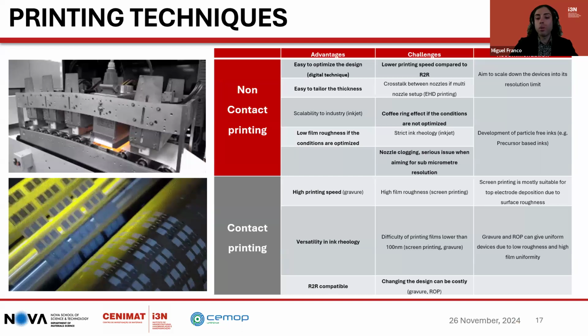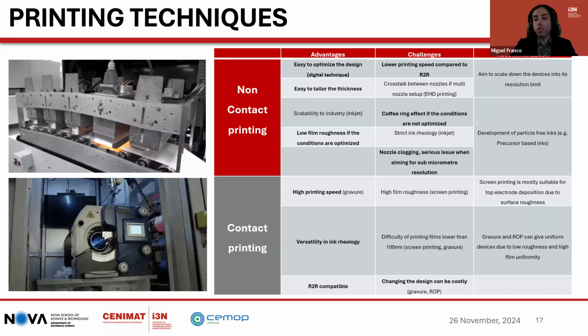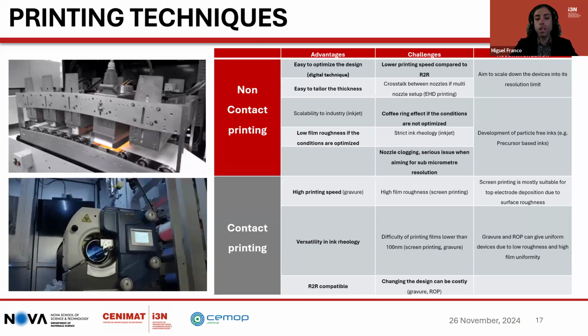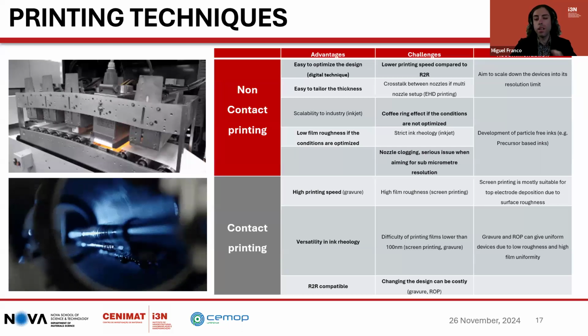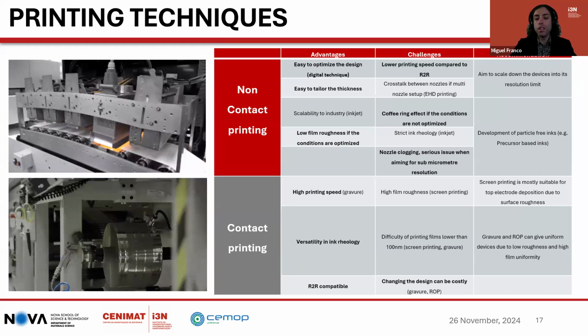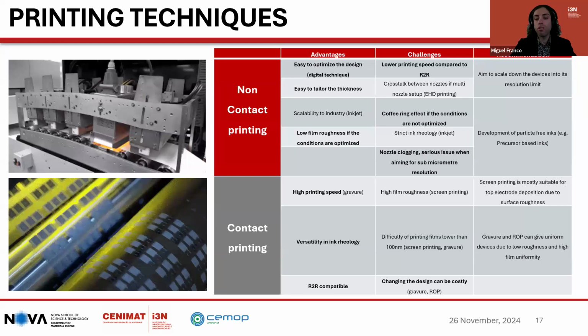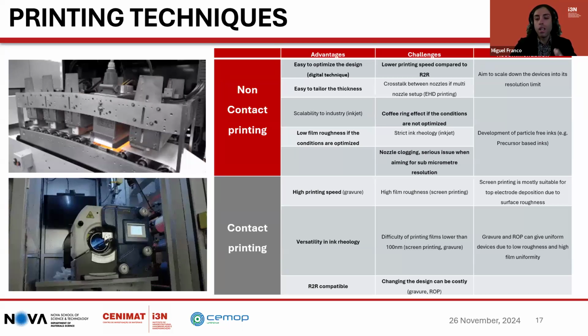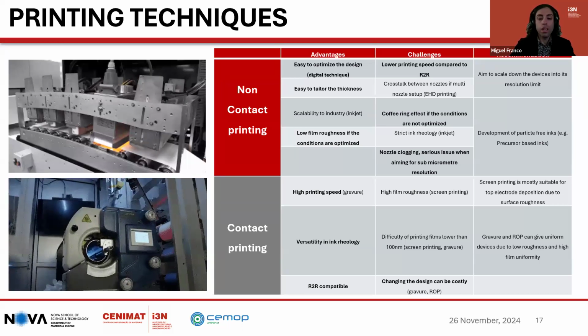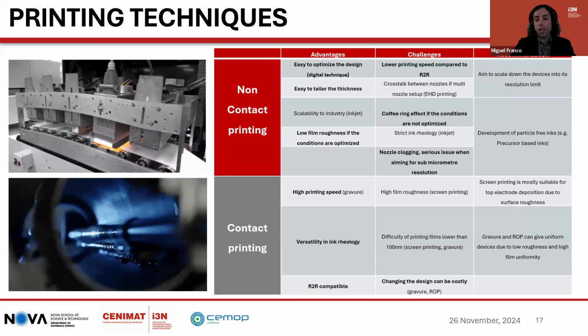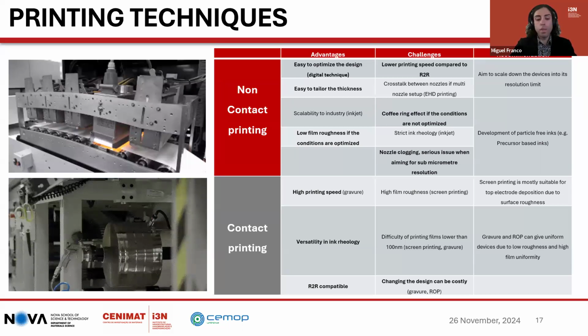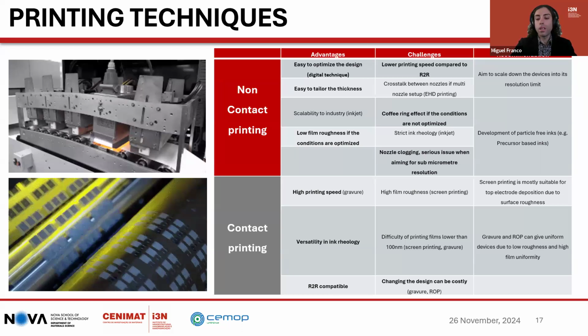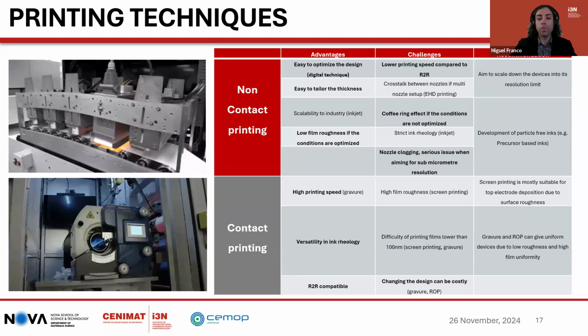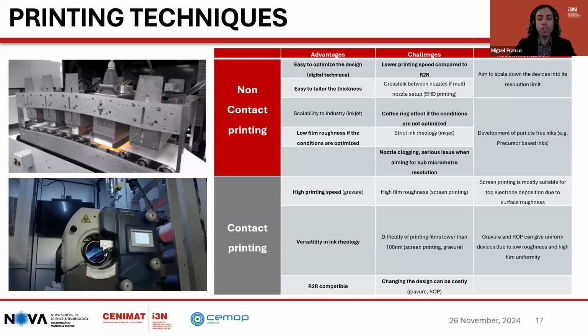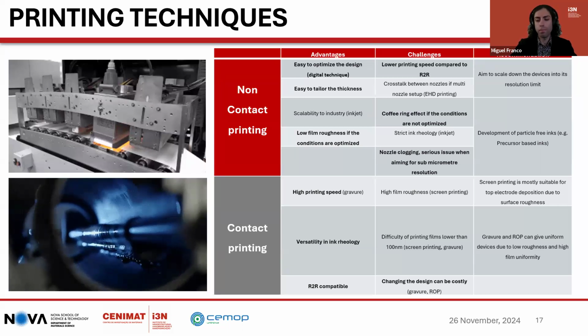On the other hand, we have non-contact printing techniques, which permit the deposition of thin films with controlled thickness. And since it is a digital technique, it is easier to change the design by changing the input file. However, the coffee ring effect and stricter ink rheology and particle size can be a constraint when formulating certain types of inks or depositing certain materials.